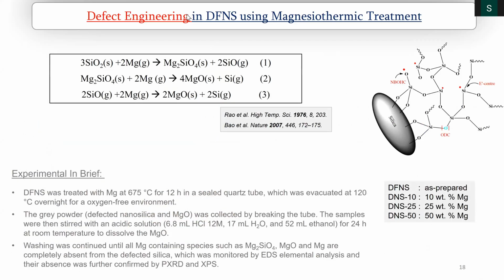There is this very old paper by Rao et al. in 1976, before my birth. They published a paper where they said, if you take SiO2 and magnesium vapors, seal it in a tube, no air, no oxygen, and heat. As soon as you heat at 675 degrees Celsius, magnesium has lots of vapors in the reactor, and magnesium needs the oxygen. Since there is no oxygen in the environment, magnesium takes the oxygen from the SiO2. It breaks one bond first and then another bond, and then magnesium becomes some sort of magnesium oxide, and SiO2 starts losing its oxygen.